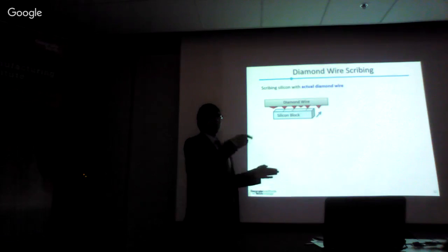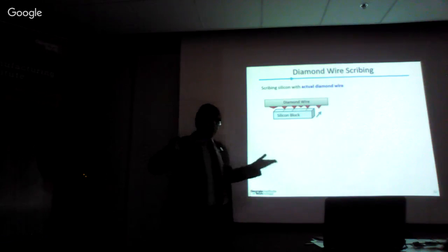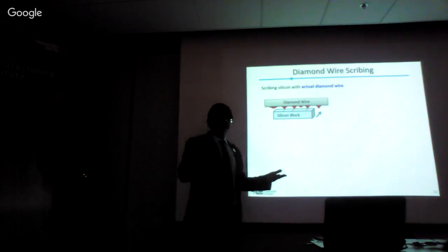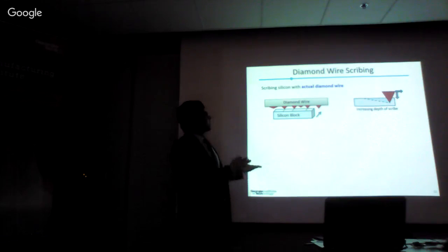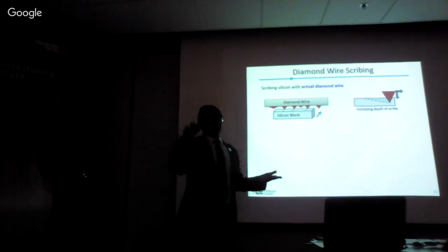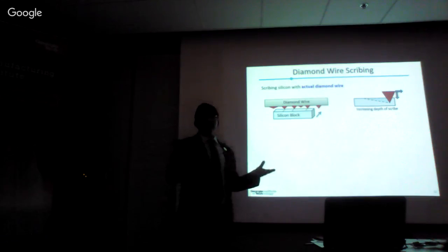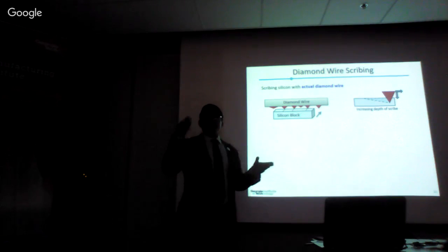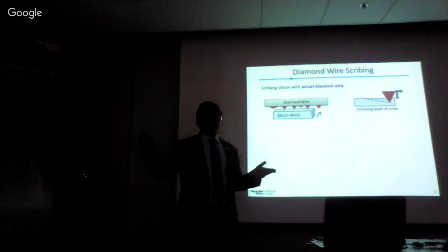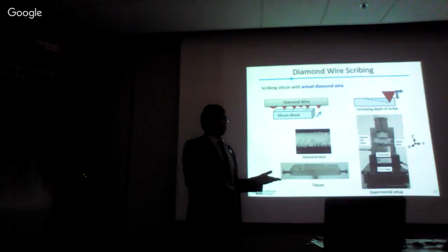We don't want the groove created by one abrasive shape to be superimposed by the groove created by another abrasive shape. We don't want any confounding effect, and that's why we are translating the silicon block perpendicular to the diamond wire. So each abrasive shape is creating a separate groove, which we can analyze and find the effect of each shape. We use increasing depth of cut scribes, as I was explaining before, so that we can find the ductile to brittle transition, or the depth at which the first crack appears. And then we can compare the different shapes.